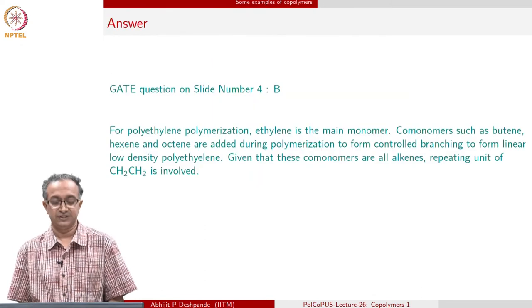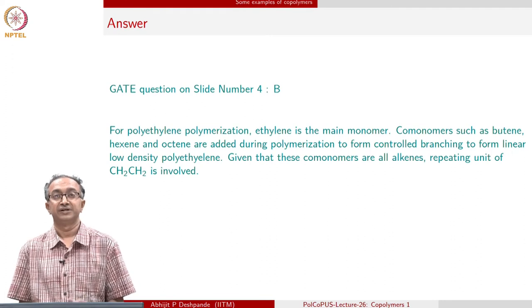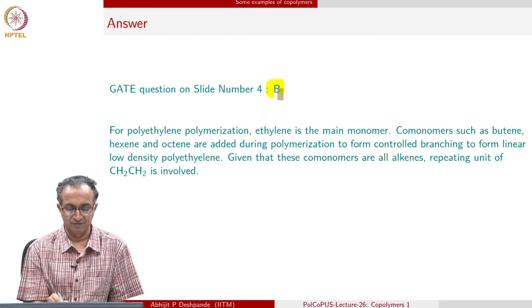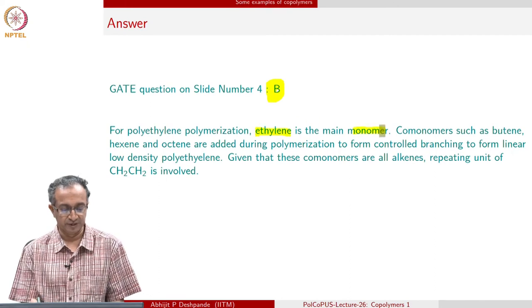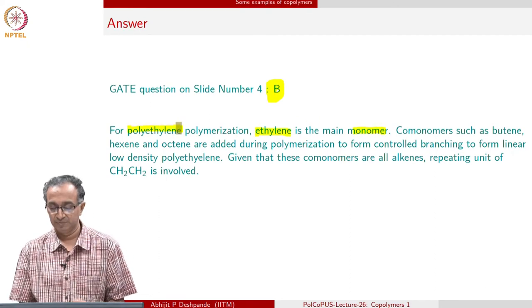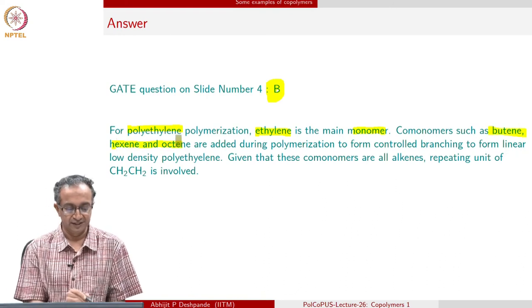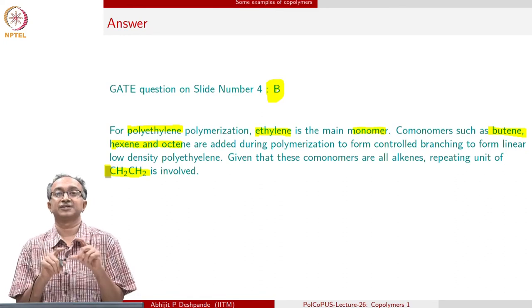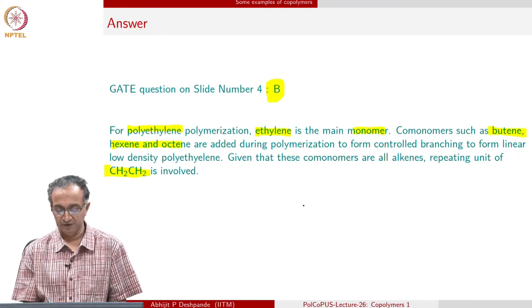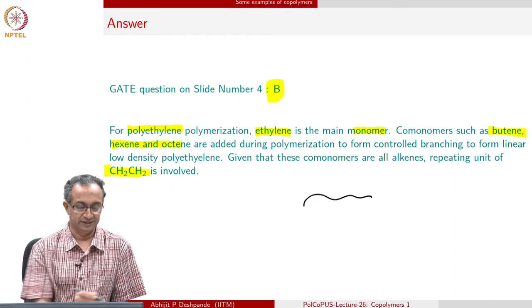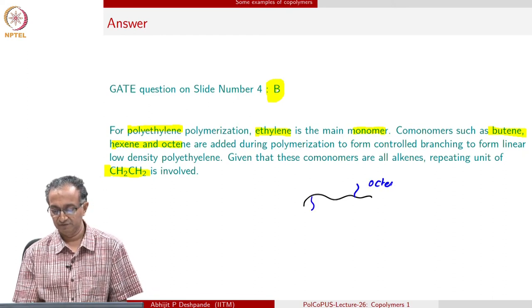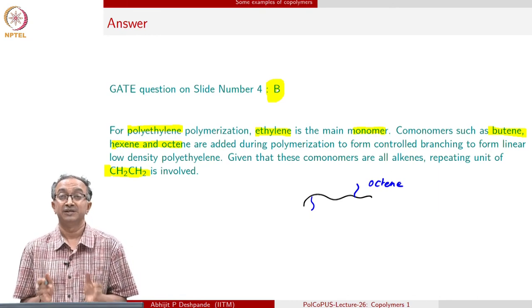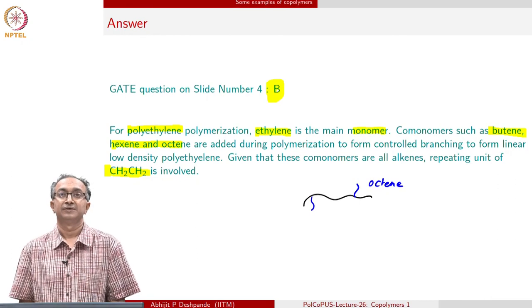With this, we will close this lecture on some examples of commercially interesting copolymer systems. You might have guessed that for polyethylene, ethylene is of course the monomer. But if you want to control the branching, then we actually use a co-monomer, and these co-monomers also have the same CH2-CH2 repeating unit. Once polymerization is done and octene, for example, gets attached to a backbone chain, we have the polyethylene backbone with octene attached. So the repeating units are still CH2-CH2, but it is in fact a copolymerization that has been effected to arrive at a controlled level of branching. Thank you.